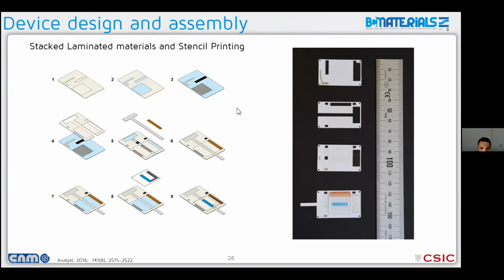So back in 2015-16, we didn't know anything about screen printing, but what we did was to use pressure sensitive adhesive. So adhesive tapes that come from the biomedical industry, because they are used as backing tapes and to make the disposable strips that you've seen in the glucose meter earlier. And what we did was we cut the protective liner on the tapes, and we put some conducting paste, graphite paste or silver paste, and we just made a stencil out of this so we could print our electrodes.